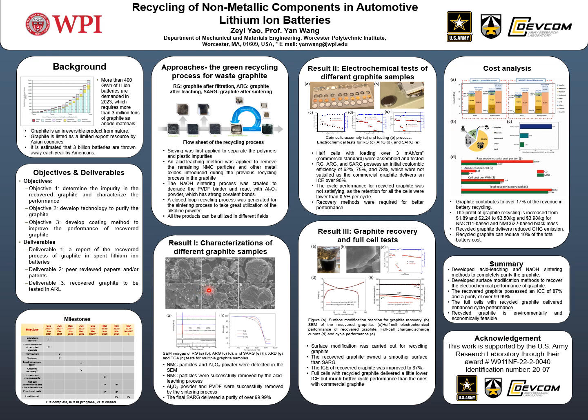Through the SEM images, we can clearly see the transition metal oxides and the aluminum oxides here during the recycling process. And finally, all the impurities are gone in figures E and F. The XRD results in figure G show that crystallinity was not affected by the recycling process, and figure H shows that the purified graphite delivers a purity of over 99.99%.